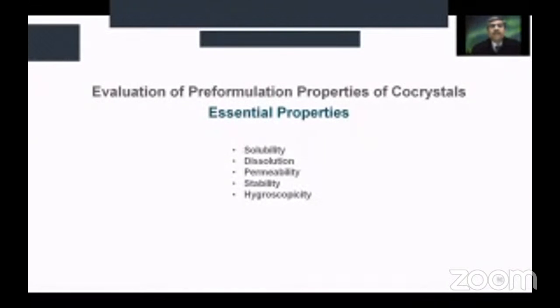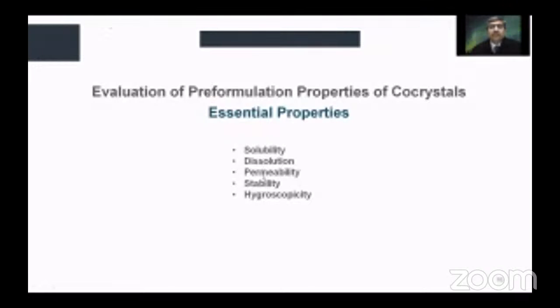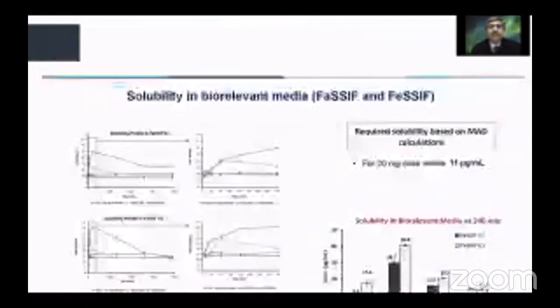We then went ahead with assessing the essential properties of the pre-formulation profiling, and we identified solubility, dissolution, permeability, stability, and hygroscopicity as the essential properties. Solubility was the primary objective for which we were creating the co-crystals, hence it had to be evaluated very, very critically. And once we change the solubility, we must also identify its effect on dissolution, permeability, stability, and hygroscopicity. And it should not happen that in the attempt to improve the solubility, we are compromising on some of the other properties, because that is going to overall affect the safety and efficacy of the final drug product.